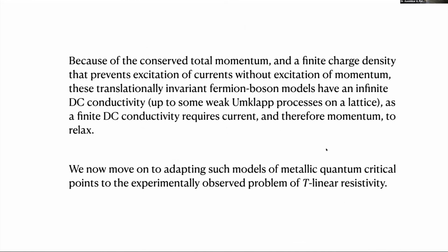But to get transport properties and strange metal behaviors, translationally invariant theories have a problem: they have conserved momentum and current. At finite density, there's overlap between the current and momentum. To relax current, you have to relax the momentum, and therefore you have to do something to relax momentum, like have some weak Umklapp process on a lattice or have disorder in the problem. And so we have to build that into these models of controlled field theories for non-Fermi liquid critical points.